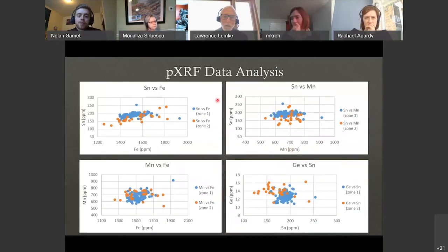We then constructed scatter plots that also show these similarities, in which iron and tin had a positive correlation, and this can also be seen with the low counts in zone 2 and high counts in zone 1. This can be seen across all the maps, including tin versus manganese, manganese versus iron, and germanium versus tin, in which zone 2 had the lower counts and zone 1 had the higher counts.